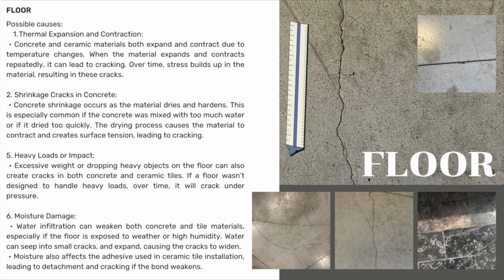Another cause could be shrinkage cracks in concrete. Concrete shrinkage occurs as the material dries and hardens. This is especially common if the concrete was mixed with too much water or if it dried too quickly. The drying process causes the material to contract and creates surface tension, leading to cracking. Another possible cause could be heavy loads or impact. Excessive weight or dropping heavy objects on the floor can also create cracks in both concrete and ceramic tiles.